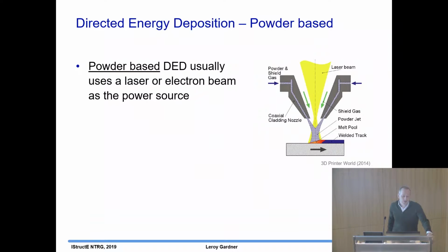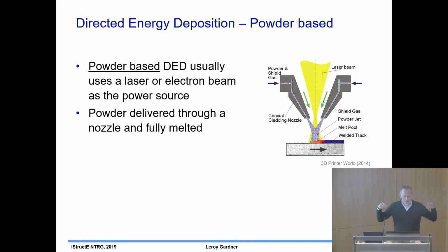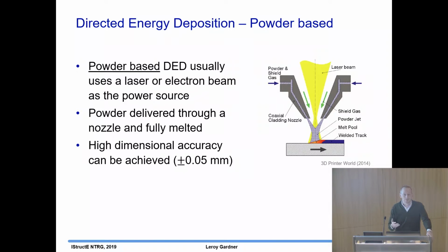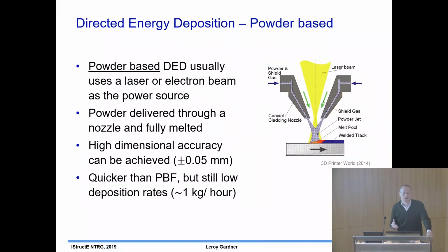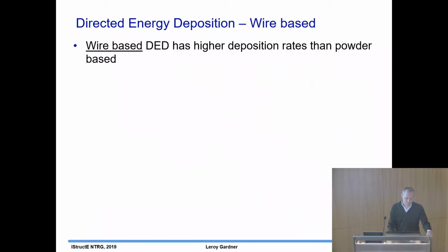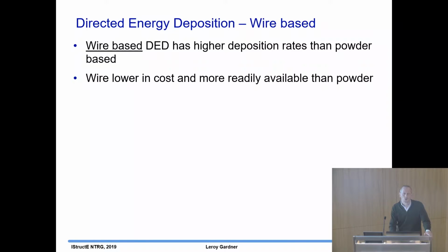The second method is directed energy deposition, and this can either be powder-based or wire-based. Powder-based directed energy deposition uses a laser or an electron beam as the power source again. The powder is fed into the beam through a nozzle. You can achieve very good dimensional accuracy, and it's a lot quicker than powder bed fusion, but it's still a relatively slow process. Then directed energy deposition, but wire-based. This time the input material is wire. The rates of deposition are much higher than powder-based, and the wire is much, much lower cost than the powder.